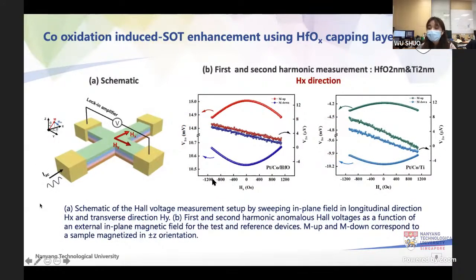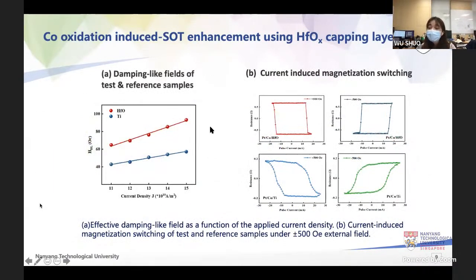Then, in order to evaluate the damping-like fields and the SOT efficiency, we do the first and second harmonic measurements. This is a schematic of the Hall voltage measurement setup, sweeping the in-plane field in directions HX and HY. And these are the Hall voltages for the HFO sample and the Ti sample along the Z orientation, which means the initial magnetization states being up and down. By fitting the experimental data at different current densities, we can get the damping-like fields. And this is the HFO capping layer sample. The SOT efficiency is about 5.1, which is 60% higher than the reference sample.